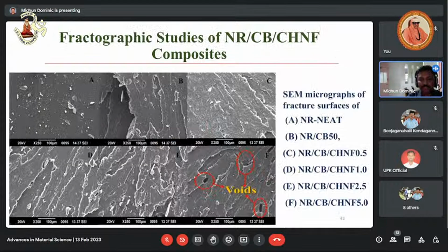And regarding the fractographic studies, we could see that no fiber pull out is seen, but at a high phr, 5 phr, there will be voids. So that might be the reason for lower tensile strength at high phr loading.